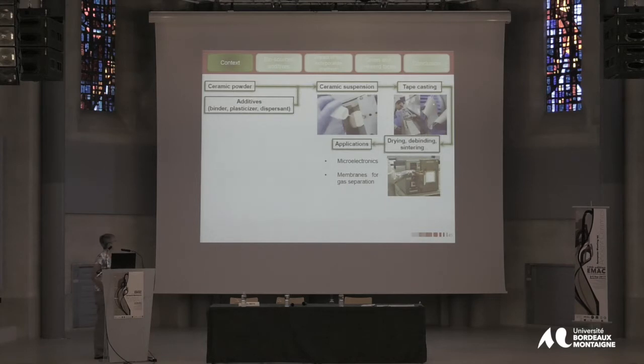And after a good drying, the ceramic tape should be very supple, but without any cracks, without any defaults. Then removal, debinding of the additive and sintering, we obtain a ceramic which can be used for applications such as microelectronics or membranes for gas separation.